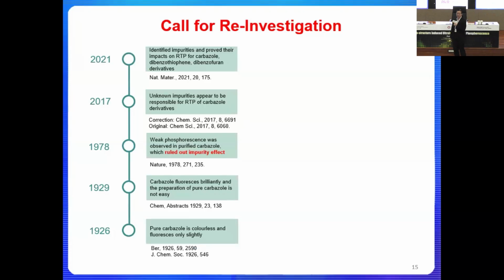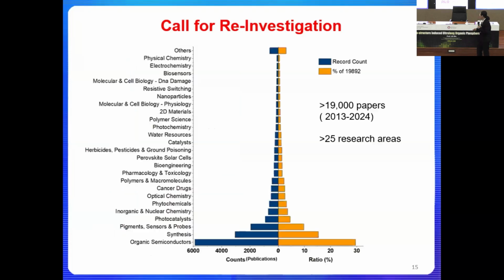Initially, we thought this was just a small incident. And when we looked into the literature, we found out this is not a small problem. This is a problem for over a century. Since nearly 100 years ago, people were discussing this phenomenon. All this light emission, sometimes it exists, sometimes they cannot reproduce it. And in between, there are debates about whether this is because of impurity or not. But fine, we're very lucky. We're the first ones to discover the impurity and explain how this small amount of impurity is making a huge difference.